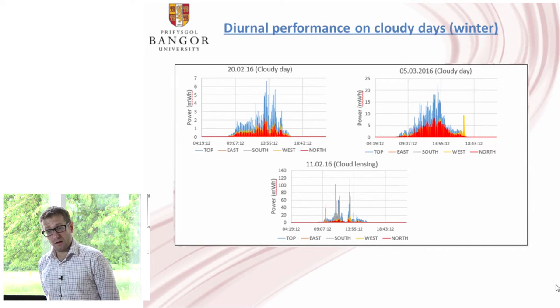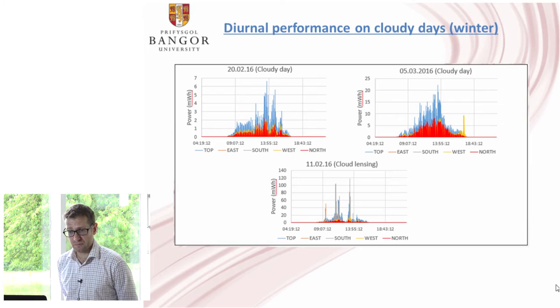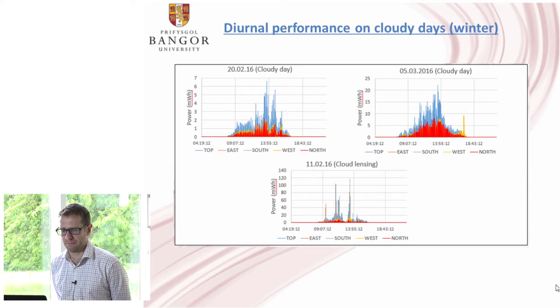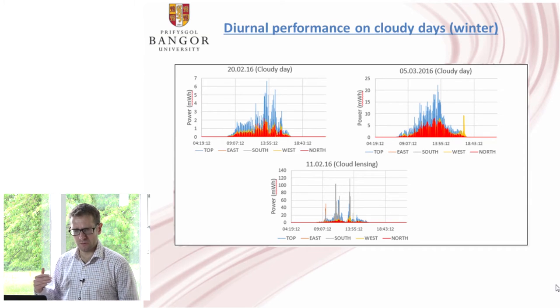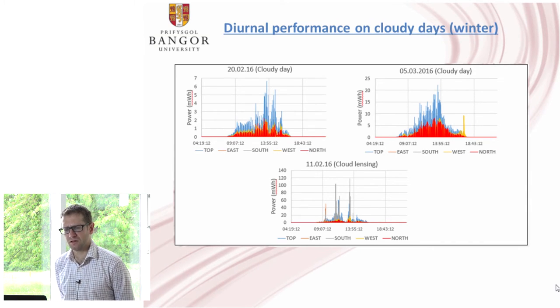So considering, first of all, our daily performance in winter, we had a very bad winter in Bangor, so we didn't get many sunny days whatsoever. But it's very difficult to pick out differences in module performance under diffuse conditions. What we tend to find under diffuse conditions, or when it's very cloudy, is that the differences in the module performance aren't significant. And we see some indication that maybe the top module gives around 20 to 30% better performance under cloudy conditions. But under these cloudy conditions, this is when the modules show the closest level of energy yield between them.